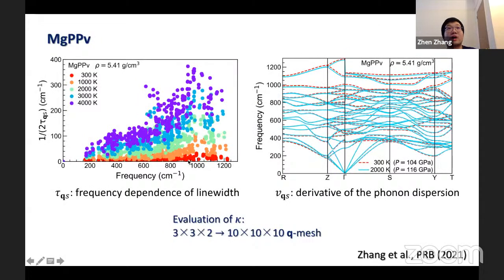Phonon quasi-particles were obtained with a 3x3x2 Q-mesh sampled by the MD simulations. To obtain converged thermal conductivity, we also want to obtain phonon lifetimes and phonon velocities with a dense Q-mesh. To do that, phonon lifetimes were evaluated with a dense Q-mesh relying on the frequency dependence of phonon line width, and the velocities were computed by taking the derivative of the anharmonic phonon dispersions. Then thermal conductivity was calculated with a dense 10x10x10 Q-mesh.